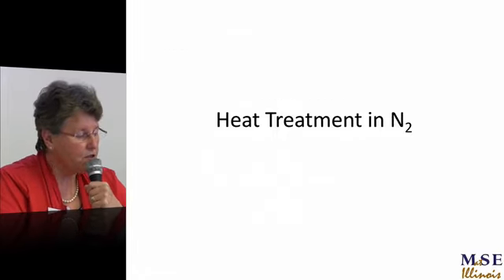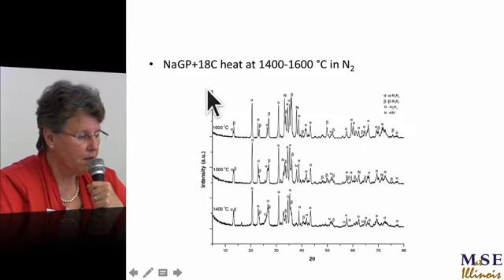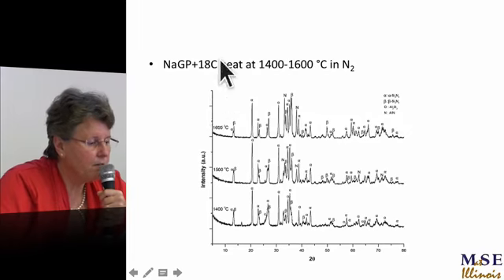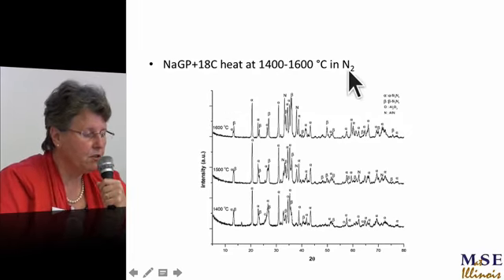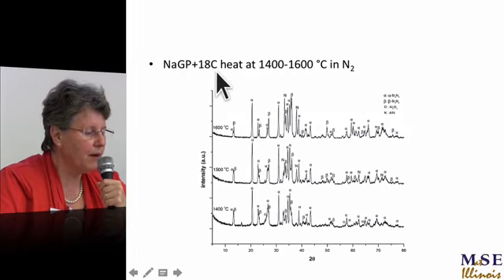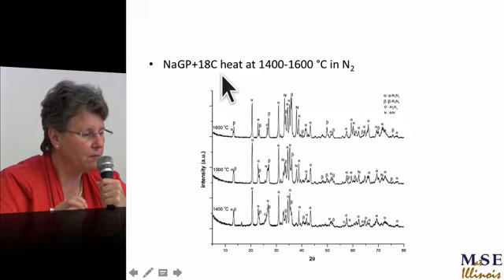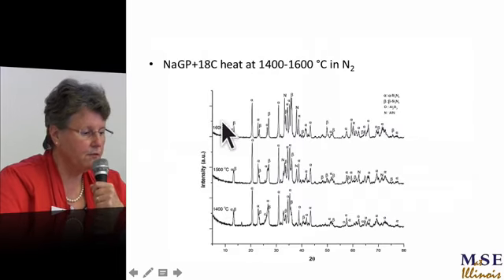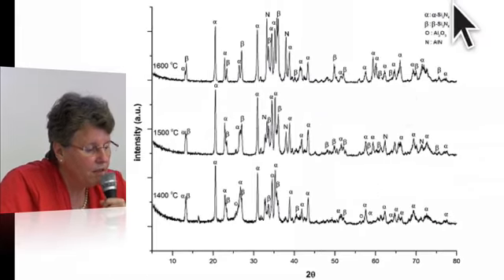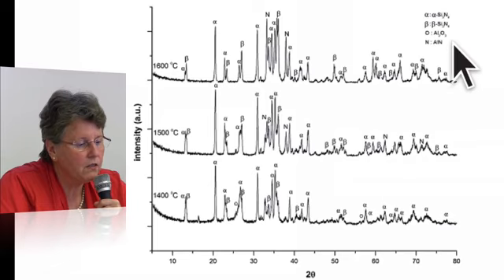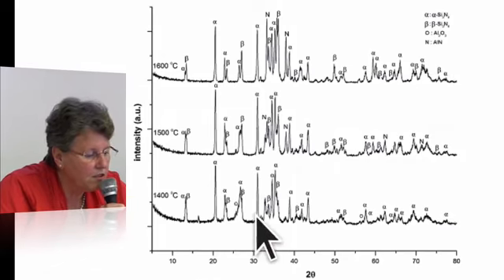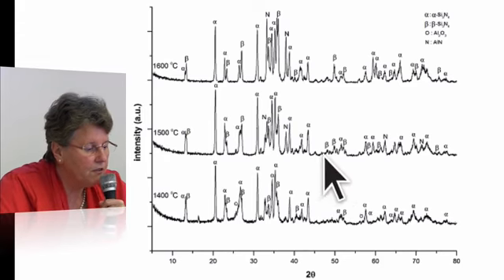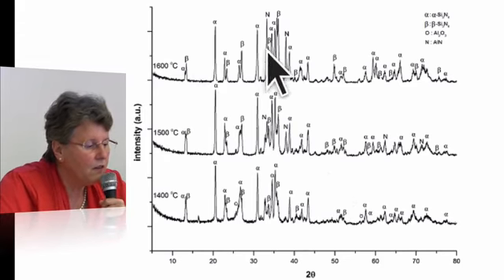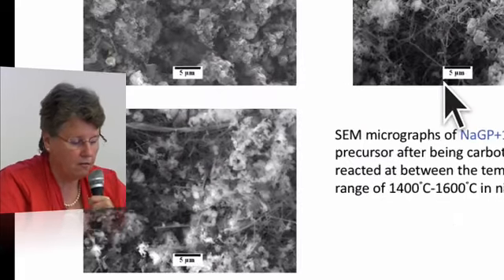Next thing is treat it with nitrogen. This is the carbothermal nitridization. So here, you take sodium geopolymer, grind it up, add carbon, 18 moles of carbon, excess carbon, to produce the reducing atmosphere. Heat it between 1400 and 1600 C, as 1400, 1500, 1600, in nitrogen. Then you'll get alpha silicon nitride and beta silicon nitride, some alumina and some aluminum nitride. So you get mostly alpha and beta at 1500, and at 1600 more beta and less alpha.